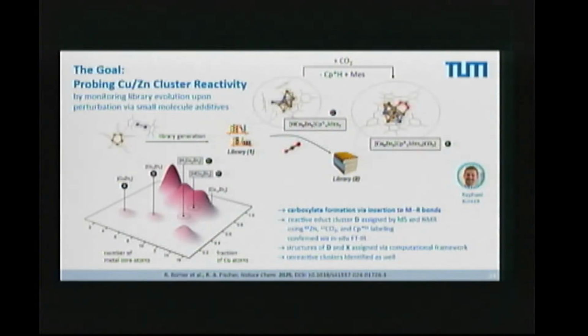Now again, imagine we have this solution. We have these 20, 30 species running around. We have a time evolution. So we initiate the cluster growth, 1 hour, 2 hours, 3 hours. If we want to probe reactivity, then we, for example, probe reactivity related to some interesting catalytic transformation. So for example, CO2 reduction. How would we do that? We have our cluster mixture, we have hydrogen gas, and we have CO2. Now we have a lot of opportunities.